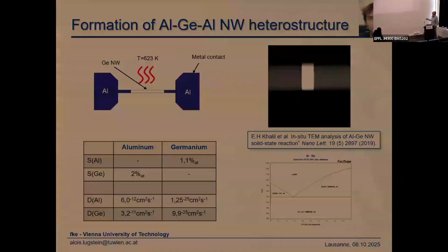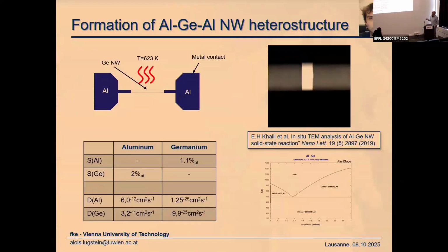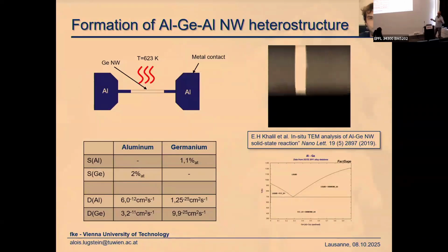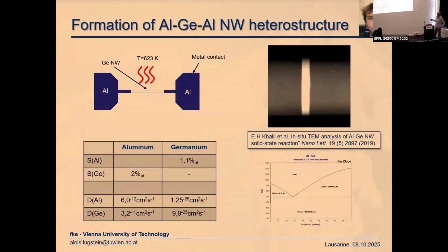Yeah, not somewhere. The germanium is diffusing into the aluminum pad. These pads are huge. This is a nanowire, let's say 100 nanometers thick. This is 150 times 150 micrometers. And the solubility is about 1% of germanium in aluminum. We did a very simple experiment. We made this pad very small, 1 times 1 micrometer. Then you see an exchange up to here.